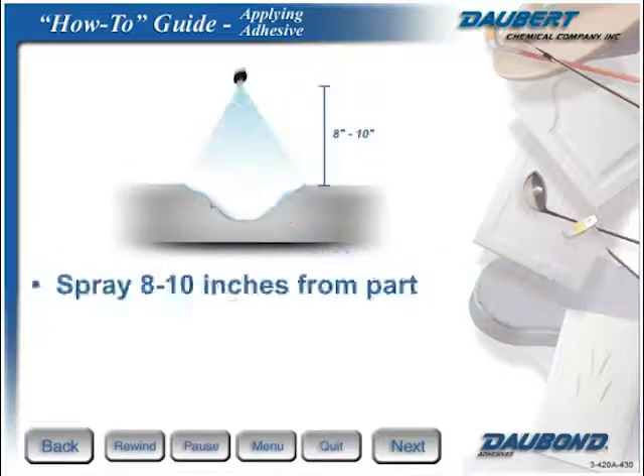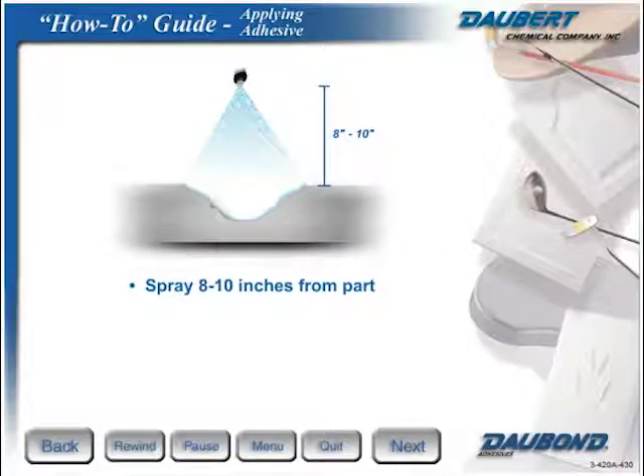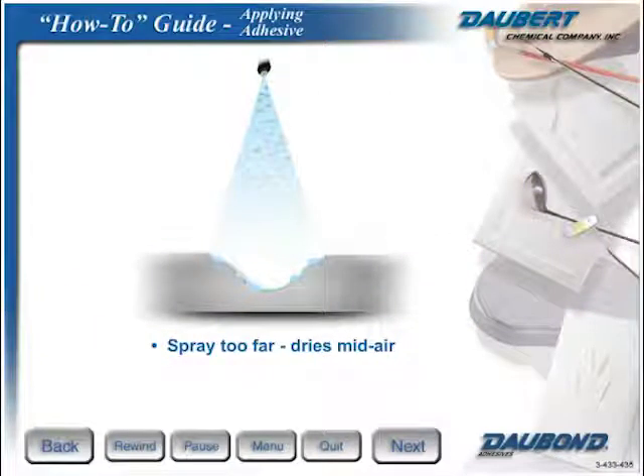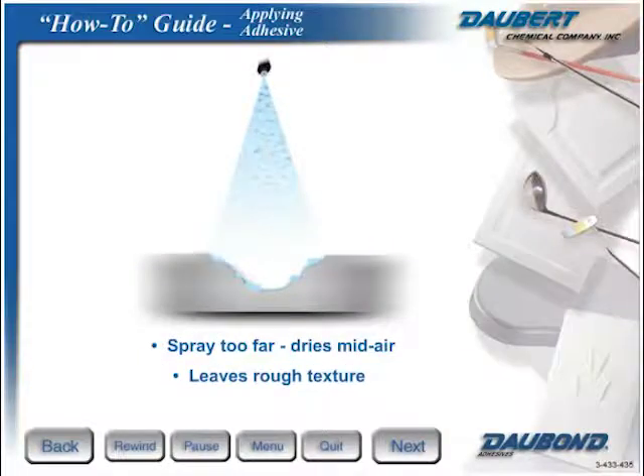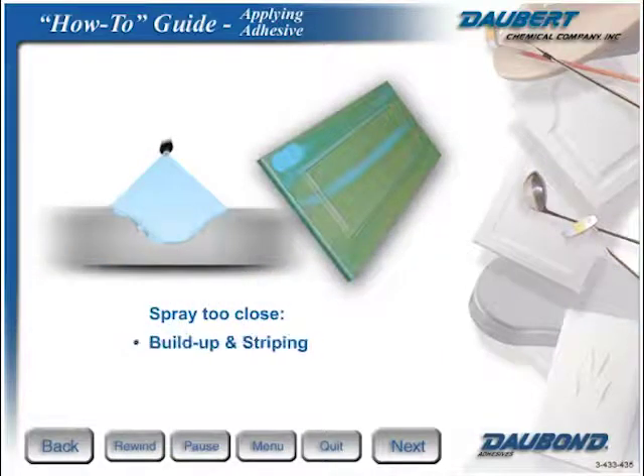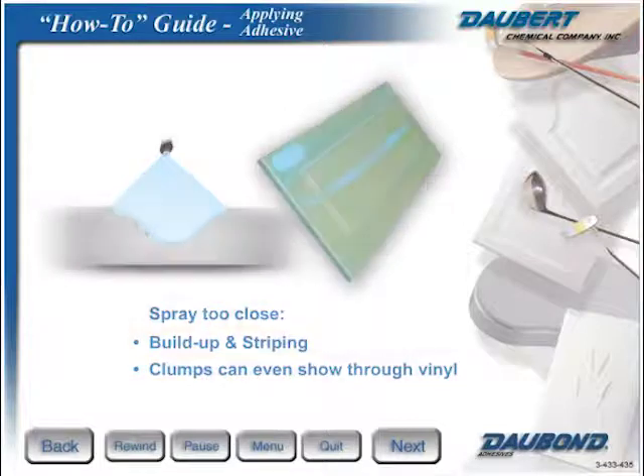Keep the gun about 8 to 10 inches from the part when spraying. Spraying too far away can cause the atomized adhesive to start to dry before it hits the surface. This can leave a rough texture on parts. Spray too close and you can get too heavy a buildup of adhesive and striping. Buildups can even show through the vinyl.